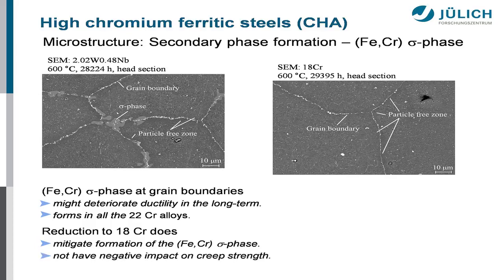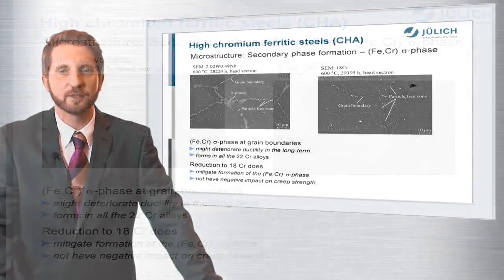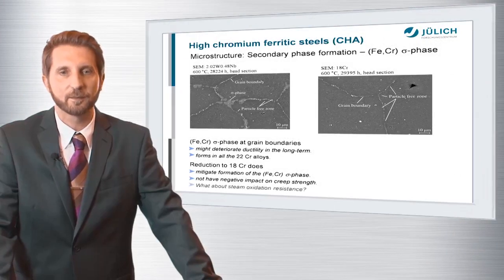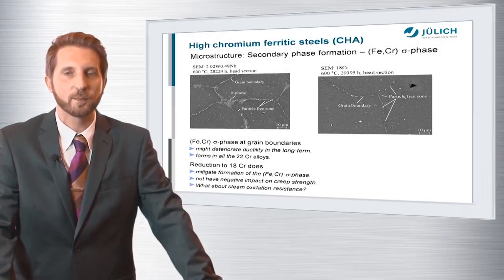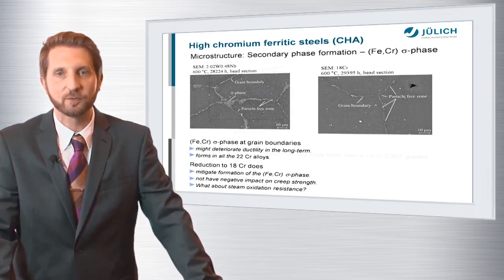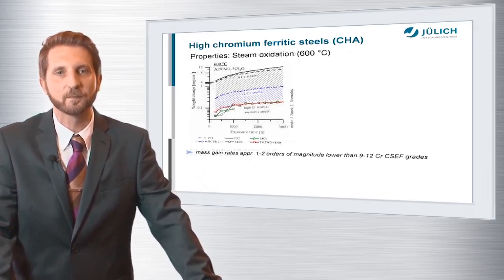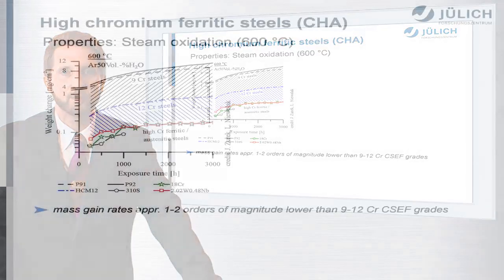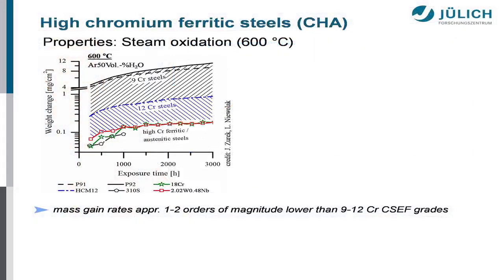And like I demonstrated to you some slides ago, this does not have negative impact on creep strength, but the question remains, what about steam oxidation resistance if we cut back the chromium content? And this is what you can see here. So here this diagram depicts weight changes or weight gains during annealing in simulated steam environment. Temperature is 600 degrees C.